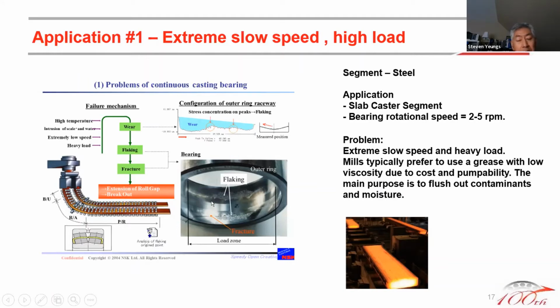And for this type of bearing, the wear will take place over a long period of time, and then flaking will gradually develop. If the bearing can be removed or replaced prior, at that point, that is perfectly fine, because it doesn't shut down the production. But flaking could further develop into fracture, and once the bearings start to break apart, then obviously the roll will not be able to rotate anymore. And that's the problem people try to avoid.